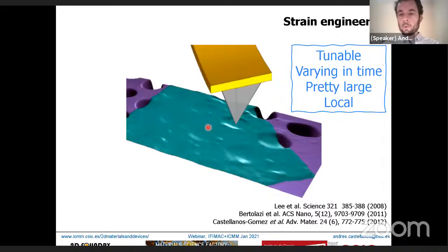On the other hand, with two-dimensional materials, because of the aspect ratio—so large and thin—you can apply strain in many ways. It's almost like a piece of paper: you can bend it, apply tensile stress directly, or try to pierce it with a sharp tip, like in this case with an AFM tip making an indentation in a freely suspended drum.